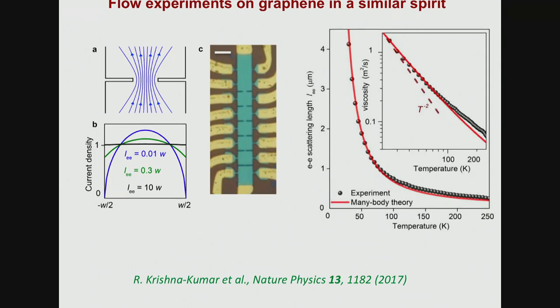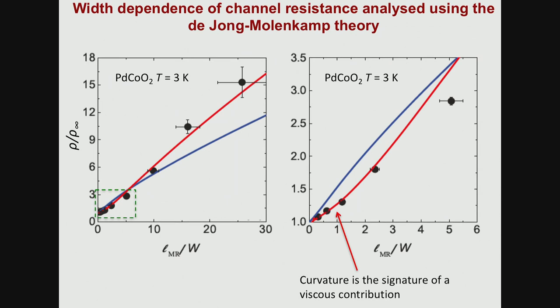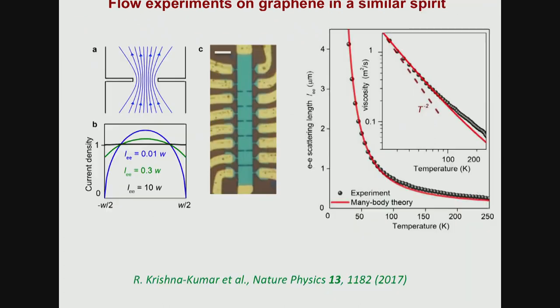So that was our experiment, and if you notice in the analysis of it, one of the things is that the conductivity of our wire in the hydrodynamic regime is predicted, or the resistivity is predicted to be lower than the ballistic resistivity for a given width over some range of widths. So a really nice experiment done by Geim's group in the same spirit a couple of years later was they said, okay, we won't go for a whole wire. What we're going to do is we're going to, and this is back to one of the questions I was asked from somebody at the back earlier on, different geometries.